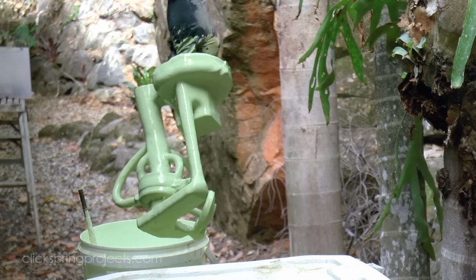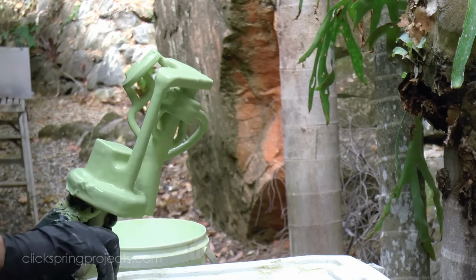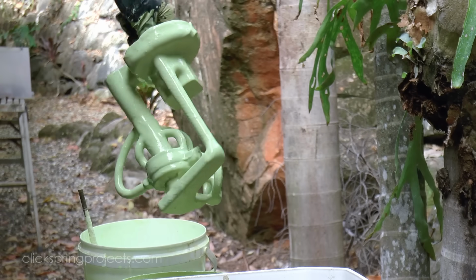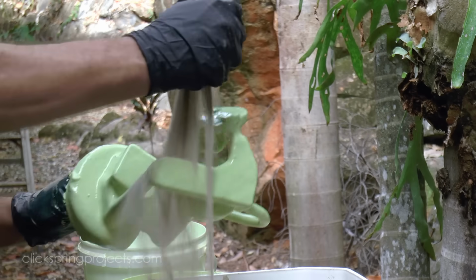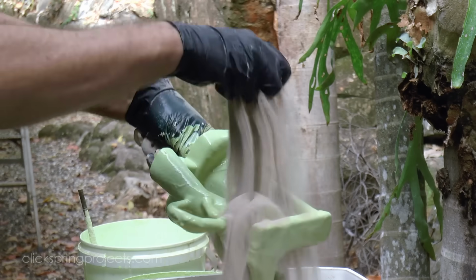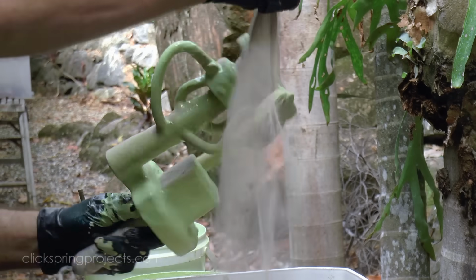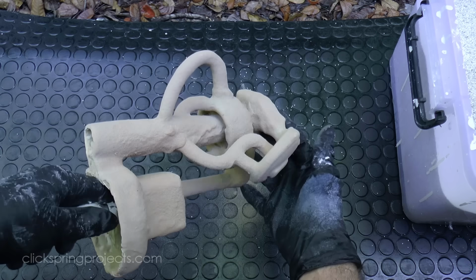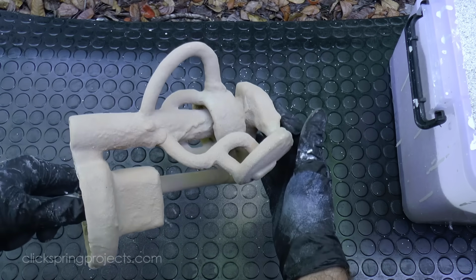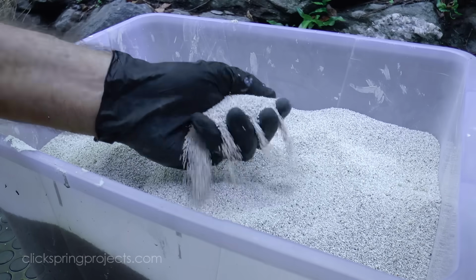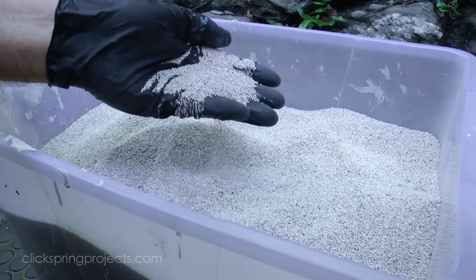As the coating gets thicker, it tends to take a little longer to dry, so depending on the weather, that occasionally slows the process to a single cycle per day for the final layers. For this particular casting, I found that I get the best surface finish results with 5 layers of zircon sand. Once the initial layers are in place, the mould can be bulked up with chamotte.